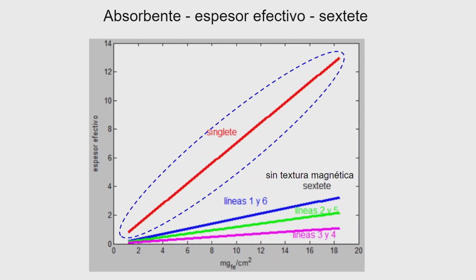And then say that you have a random distribution of magnetic hyperfine orientations in your sample, then you expect this ratio 3, 2, 1, 1, 2, 3. Okay, but it will depart from that distribution to something like 1, something less than 2, and something even less than 3. Okay, because those are the lines which are most intense.